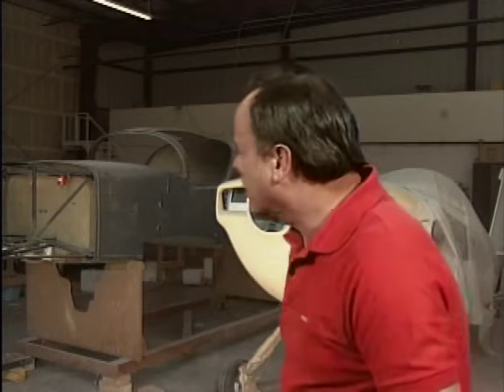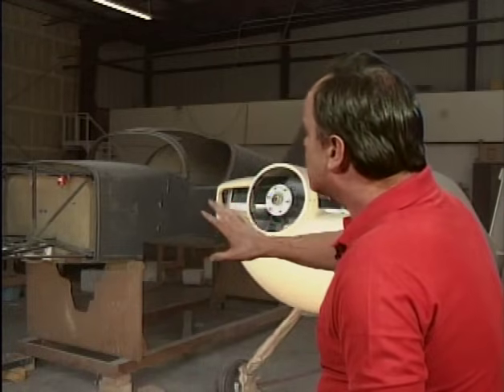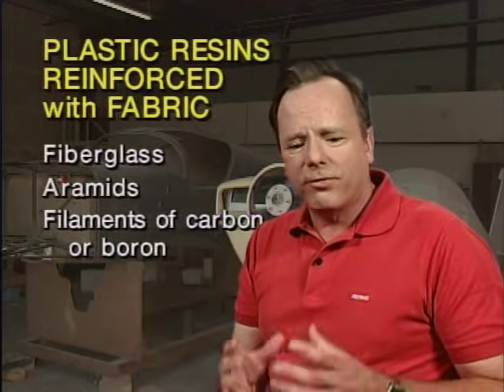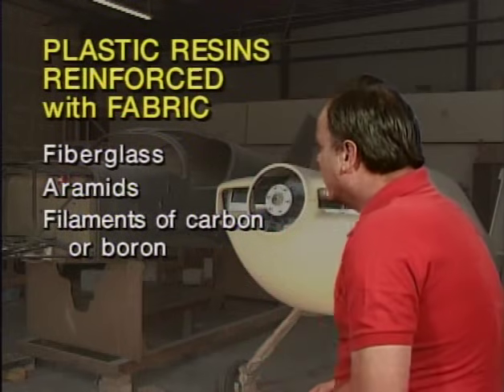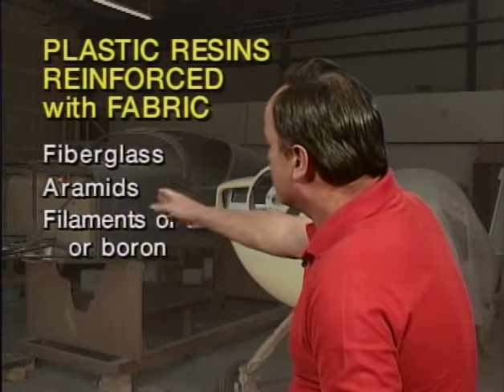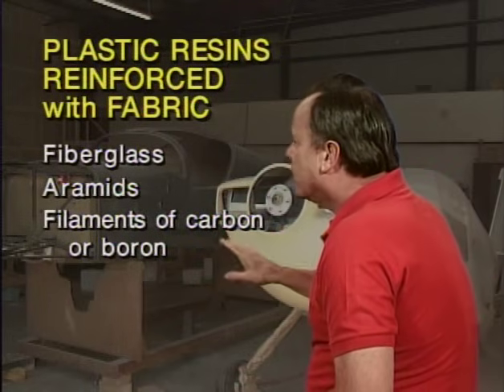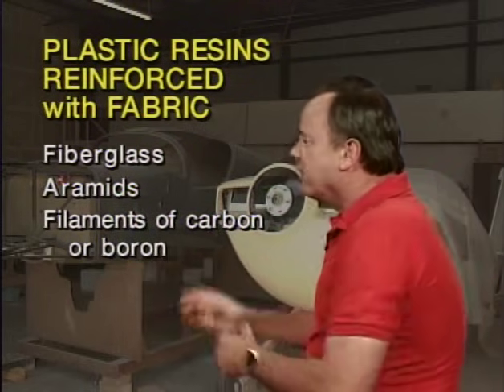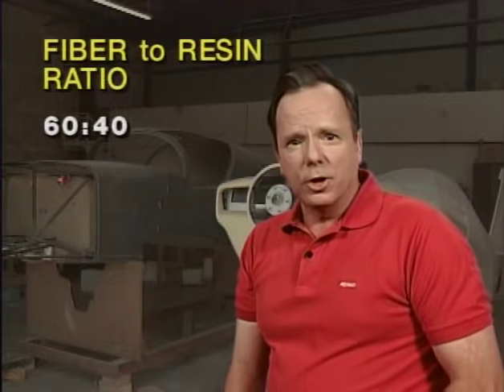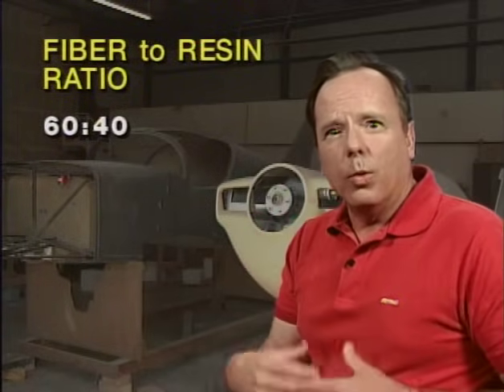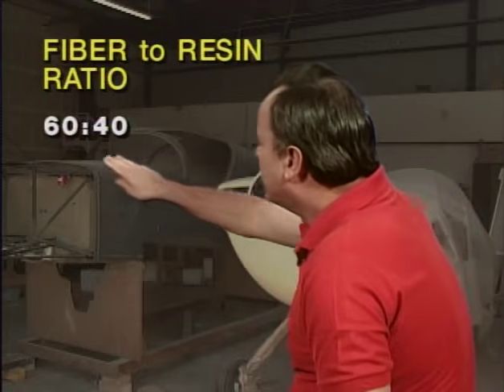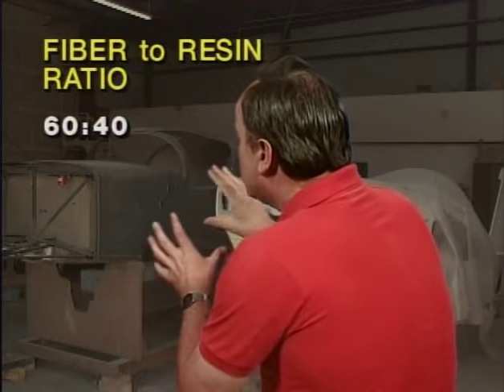Now let's talk about composite structures, often referred to as bonded structures. I think of bonding as gluing something together, but they're called composites. So let's take a look at composite structures. And composite structures very often are made of plastic resins reinforced with fabric. And the types of fabric you could put in there as reinforcement could be fiberglass, aramids, which is Kevlar, filaments of carbon or boron, and that fabric goes inside the resin. Now the fiber to resin ratio for advanced composites, what they call wet layups, is generally considered to be 60-40, and that's fiber to resin, and that gives you the best strength.